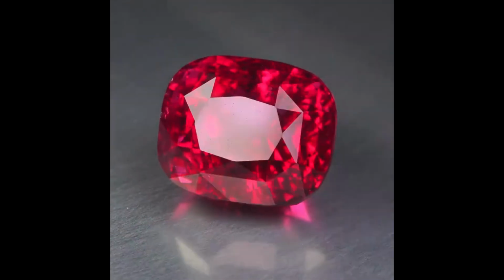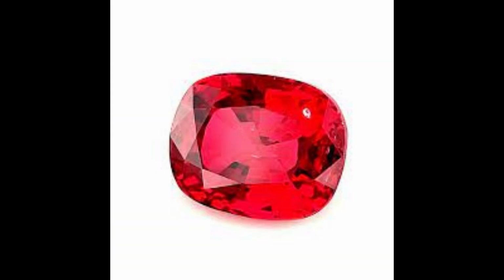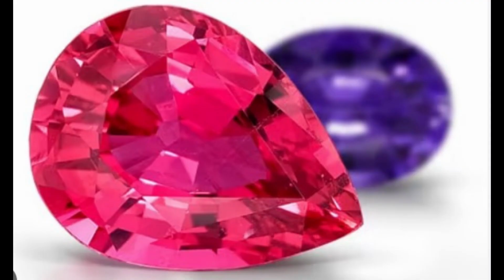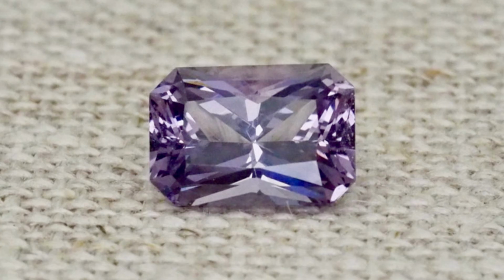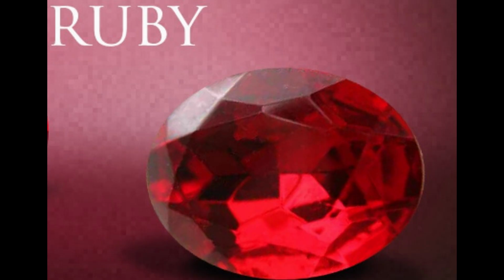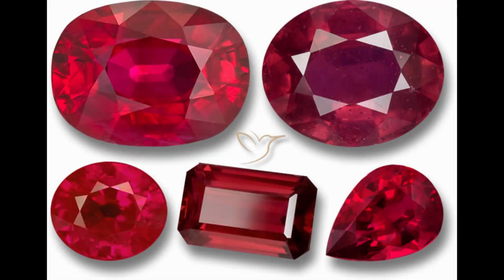We could also look at pleochroism. You will not see any in the spinel, but you will be able to see, let's say, an orangey tone, for example, in a ruby. As soon as you see a second color, you know you're not looking at a spinel. So hopefully that clears it up, and that is why we are able to say with certainty if we're looking at a ruby versus a spinel.